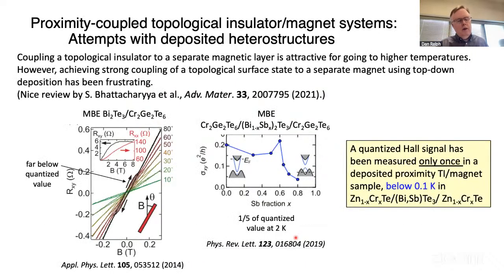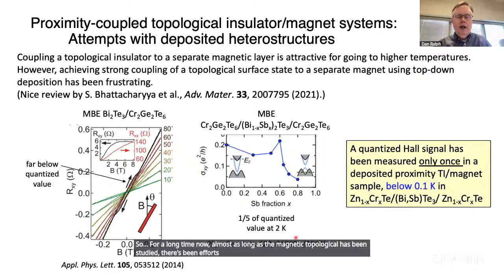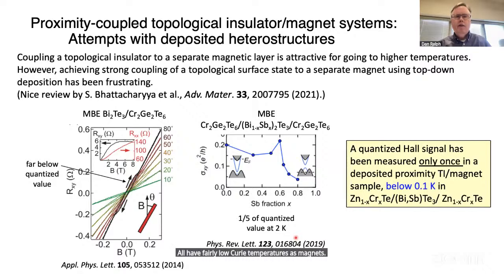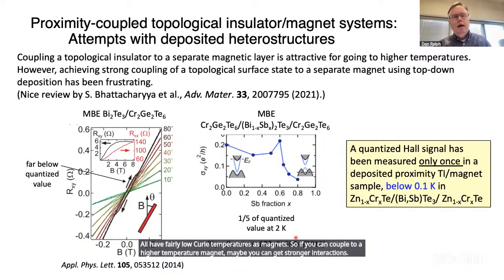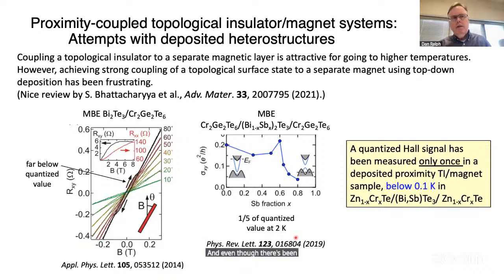Okay. So for a long time now, almost as long as the magnetic topological insulators have been studied, there's been efforts to try to reach higher temperature scales by coupling 3D topological insulators, using proximity coupling to an external magnet. And the logic here is that the magnetically doped topological insulators themselves all have fairly low Curie temperatures as magnets. So if you can couple to a higher temperature magnet, maybe you can get stronger interactions. And even though there's been a lot of effort about this, the results have been sort of disappointing so far.